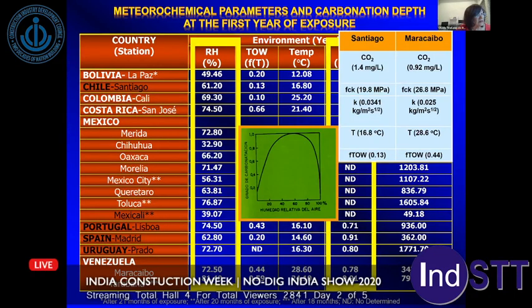Nonetheless, once the concrete is carbonated, a relative humidity bigger than 80% should be present for active reinforcement corrosion to happen. So the time of wetness fraction, which is the time a metal plate will remain wet during 1 year, may be used as 13%, which would indicate that even though it is the most easily carbonated concrete, the environment does not have enough moisture to initially induce and maintain the reinforcement corrosion.